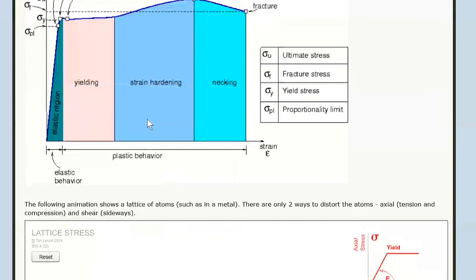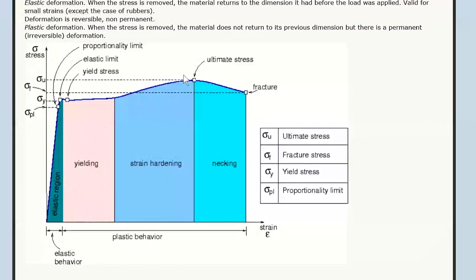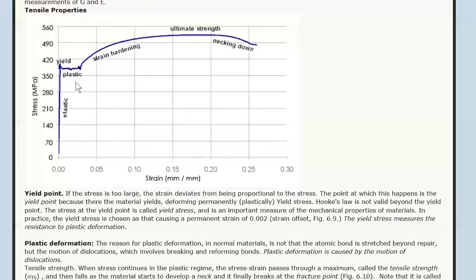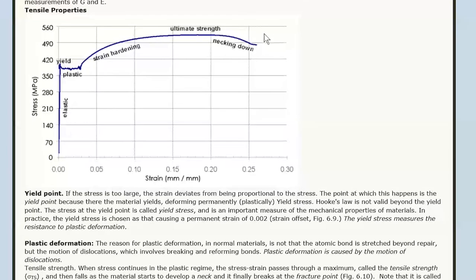This graph is the genuine stress-strain curve for mild steel, directly from a tensile testing machine. Look how steep the elastic region is — it's almost a vertical line. The elastic stretch is tiny, about a tenth of a percent, and you wouldn't see it by eye. You could accidentally go over the yield point without even noticing it if you turn on the machine too fast. If you're going at constant speed, it could take you like an hour to break the whole thing because mild steel has a very long plastic stretching stage — it could be like 20% longer.